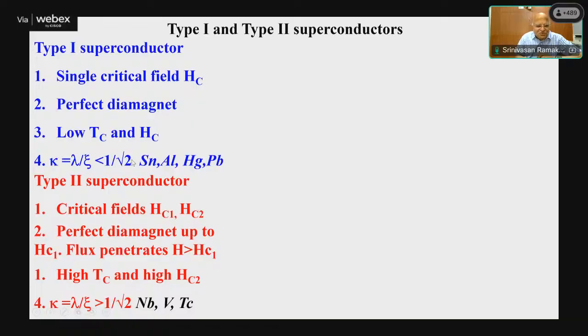This 1 by root 2 is coming because the surface energy turns from positive to negative when kappa is less than 1 by root 2. This can be derived, I used to derive it in my class, but that derivation is a little longer. And that was also derived from the Ginzburg-Landau theory, which showed that at the critical value of 1 by root 2, it changes from a type 1 to a type 2 state.